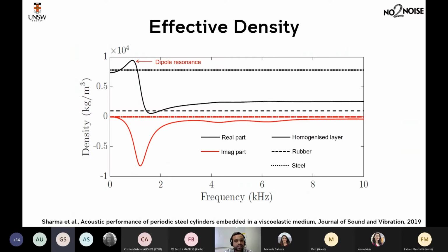This is showing the effective density of different materials. First, this is for the homogenized layer, made by homogenization of your hard cylinders in a soft medium. These are the density values for rubber medium and for steel. As you can see, the effective density of the homogenized layer can vary a lot with respect to frequency. And again, this is the real part and this is the imaginary part. The imaginary part is already negative, but even the real part can go negative at certain frequencies.